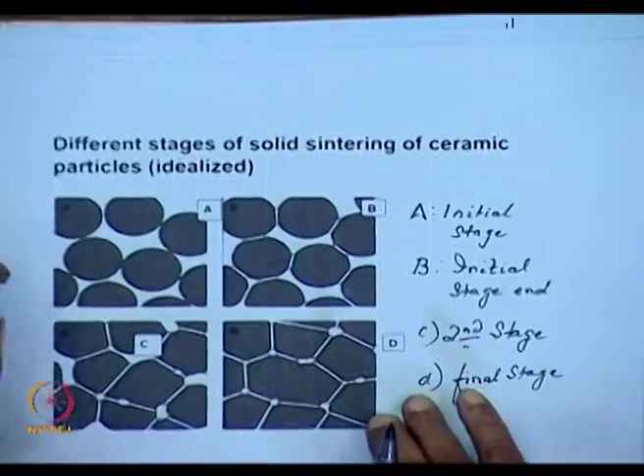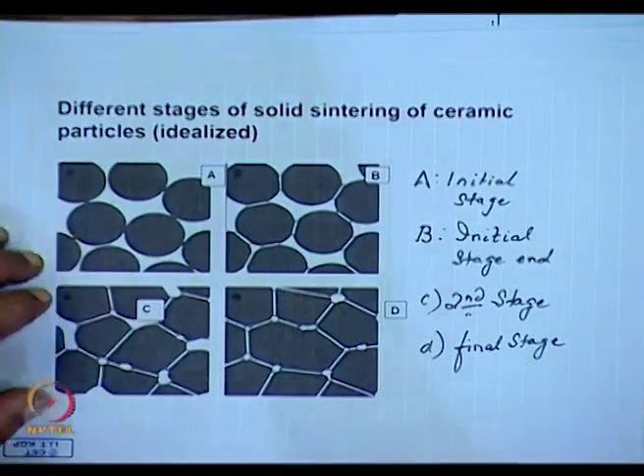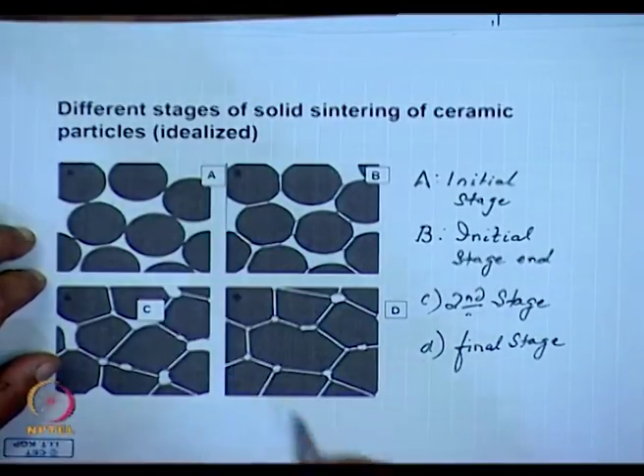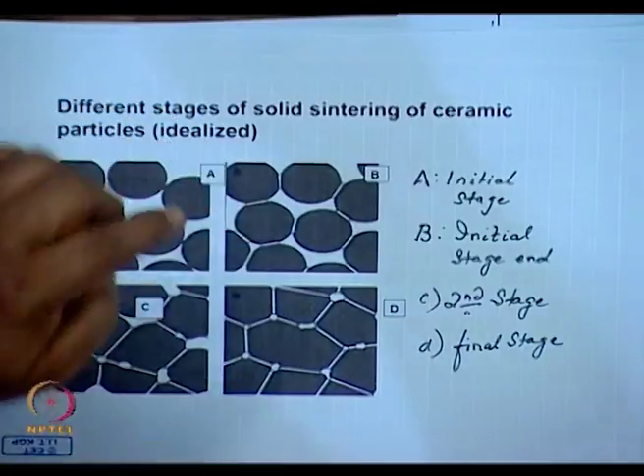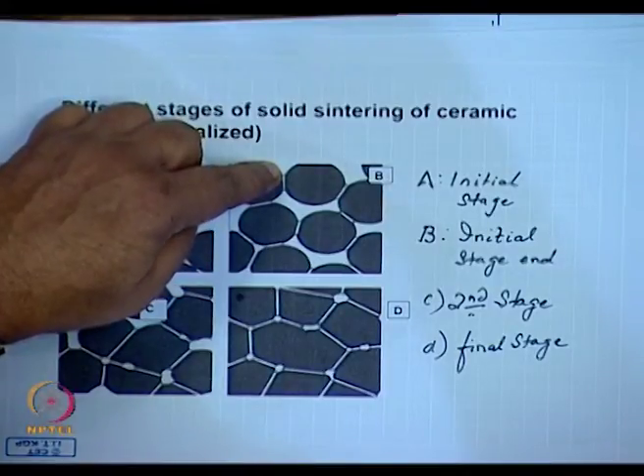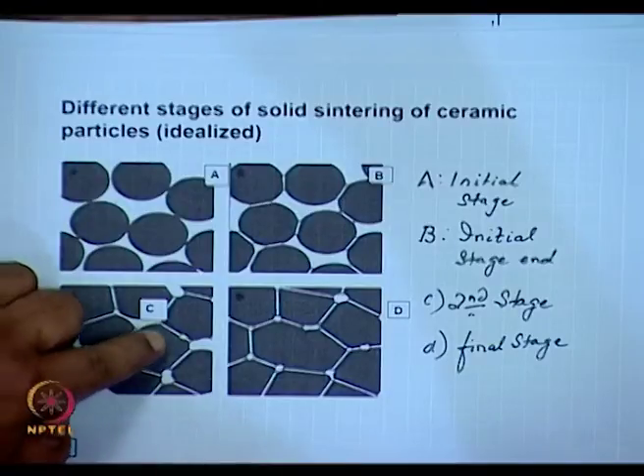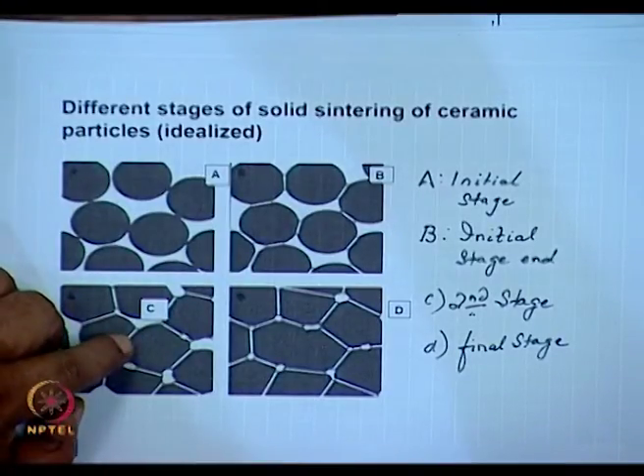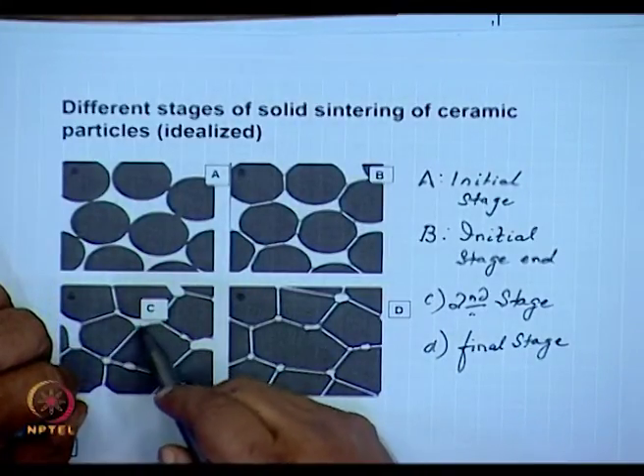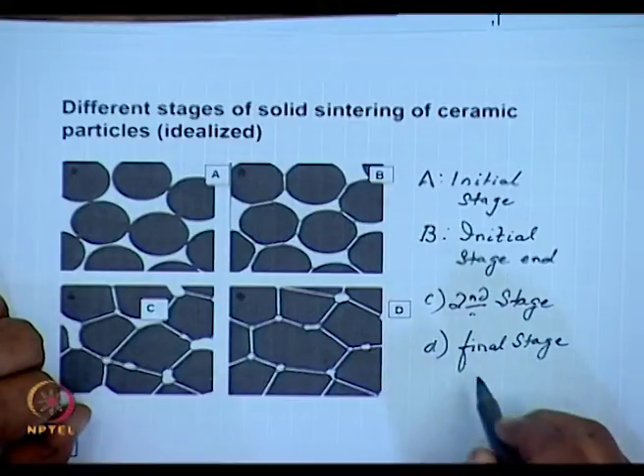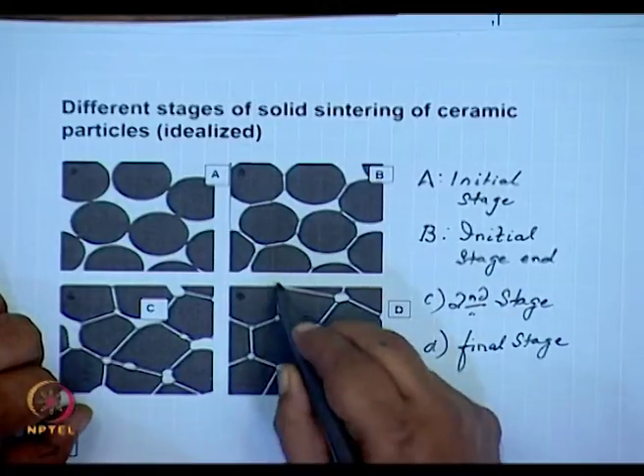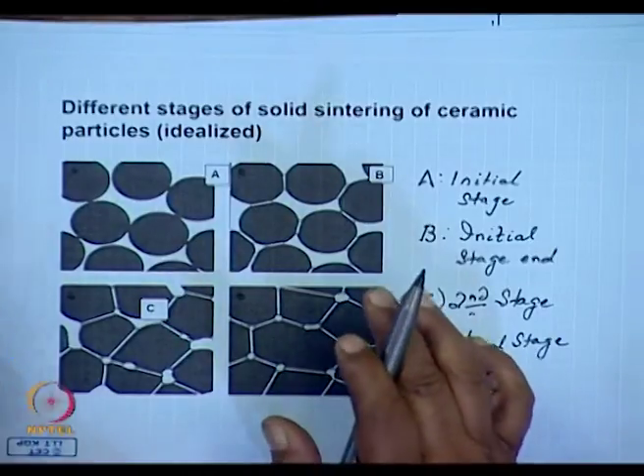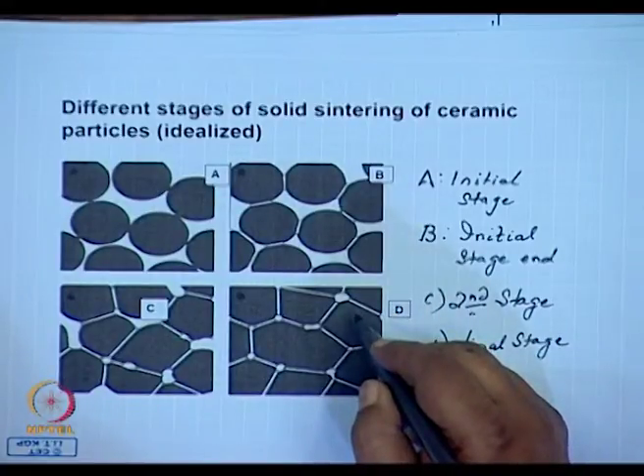Again, to review the sintering process: in the initial stage, mass transfer along grain boundaries has occurred, leading to development of the necks. As sintering proceeds, the grains have flattened out, the grain boundaries have increased, and the pores have started concentrating at the grain boundaries. At the final stage, they are only at the corners, leaving the grains with very few sizes.